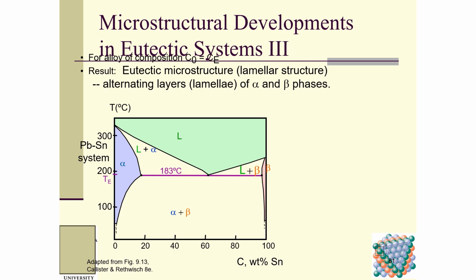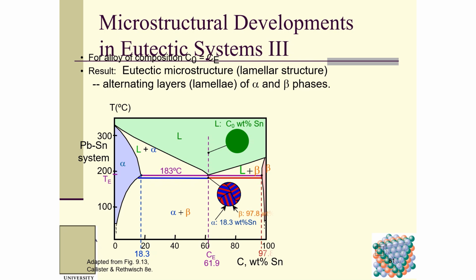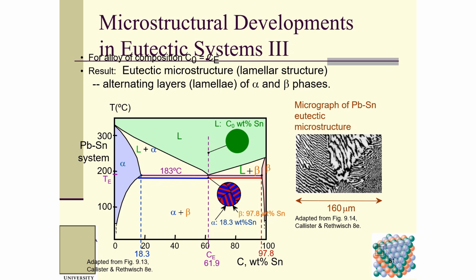For another range, for this part, eutectic microstructure, lamellar structure. Okay, so lamellar structure, you can see lamellar. What is lamellar? Alternating layers, lamellae of alpha and beta phases. You can see this one. So you can see lamella. Lamella means alternating layers of two different phases. Very, very beautiful. You can still use our lever rule to calculate the weight fraction. And this is a micrograph of this system. It's very, very beautiful.